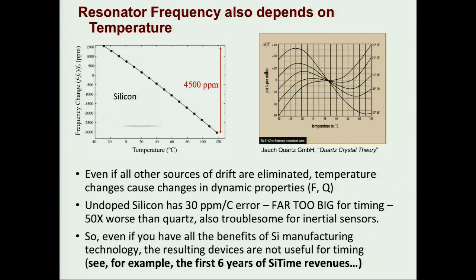4,500 parts per million over the room temperature sort of operating range of a commercial product. Quartz is maybe 50 to 100 times better. And this has always been the number one reason the quartz was the preferred technology all along. And even as SiTime was getting going, we all knew this was the barrier we had to climb. We could make stable silicon. We could do all the temperature compensation in the world, but we started out a factor of 50x behind quartz. And the time and money and effort you spend to overcome that factor of 50 is a real problem.